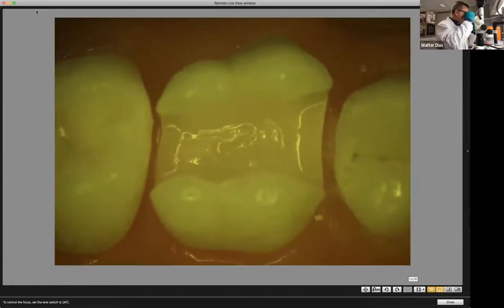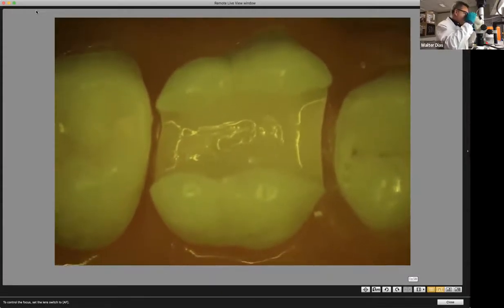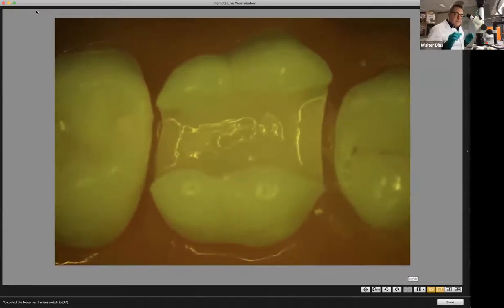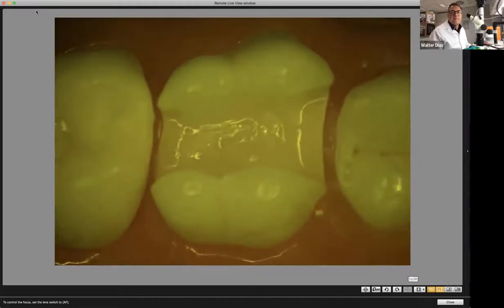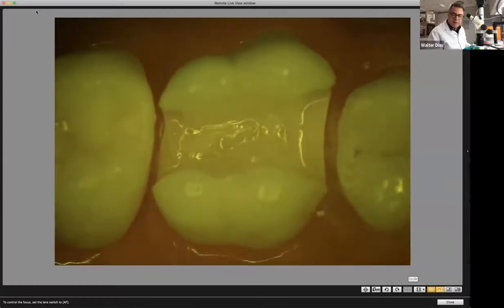Only after removing the excess can we dry this adhesive. And this is singularly the largest cause of insufficient adhesion when applying a universal adhesive like this, because every universal adhesive contains water. It has to, because it's also self-etching. So you need to dry this properly. If we look at the instructions, there you go. It calls for 5 seconds.